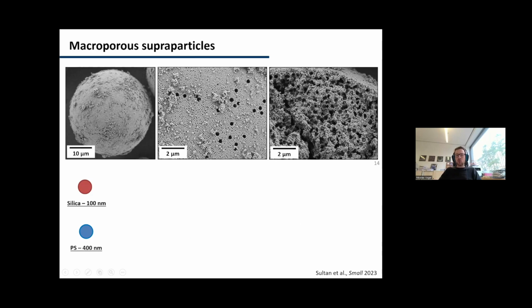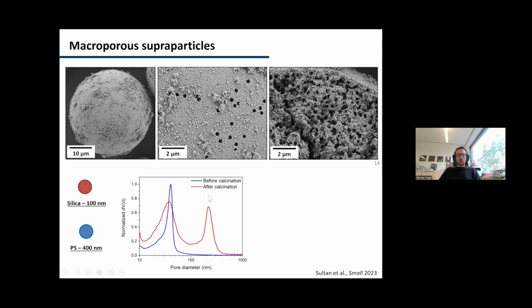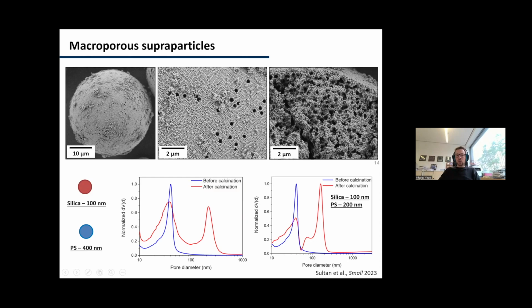You see how they penetrate here. If they're larger, they accumulate more on the inside. And what you see here before calcination, we only have that pore size distribution coming from the interstitial sites. And upon calcination, we can then introduce a larger peak that could be used for transport pores and so on. Now we can also change this, and depending on how big we make our polystyrene particles, we can then control that larger pore dimension as well.